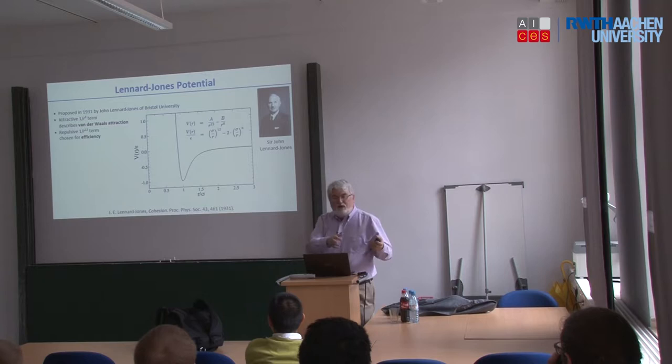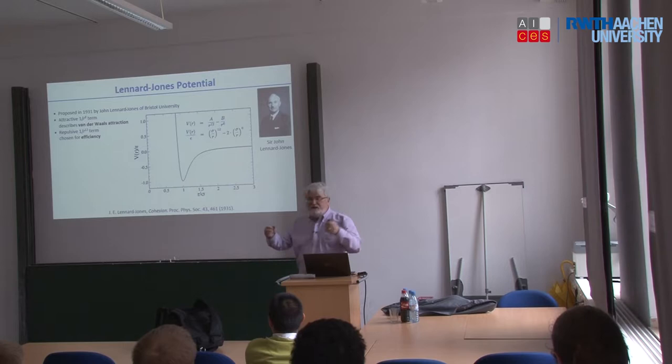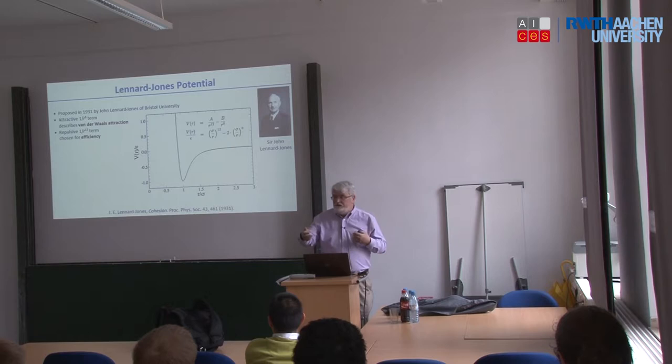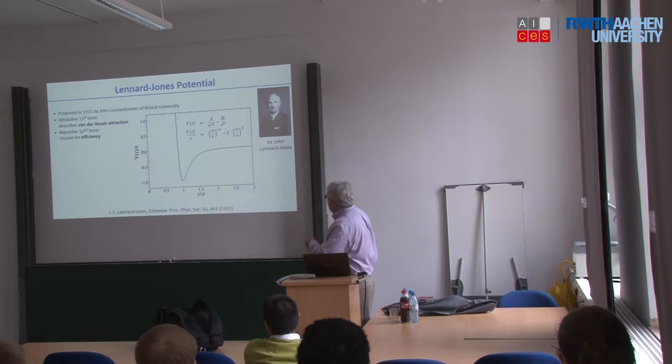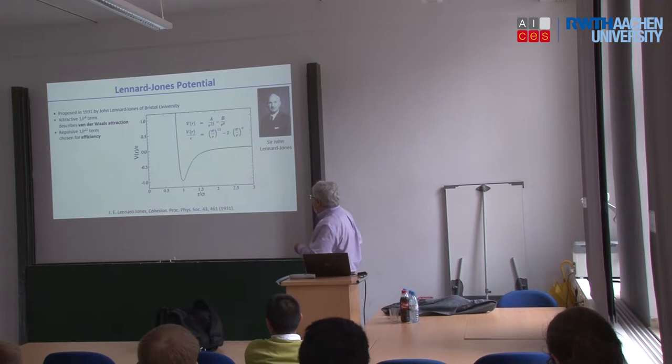Okay, so here's the energy versus separation. Here's zero. Far, far away, the energy between two noble gas atoms is zero. But it is attractive. It's the van der Waals interaction. We know it's always going to be slightly attractive. So this is zero at infinitely far away, but any finite distance is a little less than zero, and it's getting stronger as you get closer. So that explains that downward part. Now you start to get real close, that binding gets really strong.